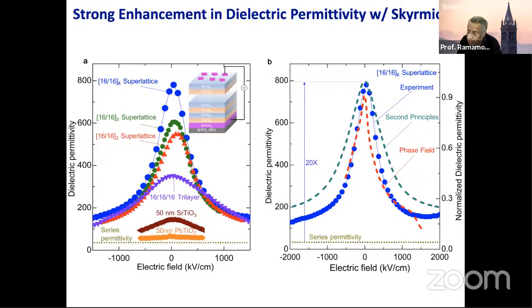What happens if you apply an electric field? And it turns out that when you apply an electric field, that dielectric permittivity will change by about 75%. And by the time you hit about 1.5 megavolts per centimeter, which is about 15 volts across a 100 nanometer sample, you can bring the dielectric permittivity down to something that looks very normal. This is very reversible. In a few minutes, I'm going to tell you that this is a topological phase transition. It goes from a structure that has topology in it to something that doesn't have topology. It's a field-driven topological phase transition.